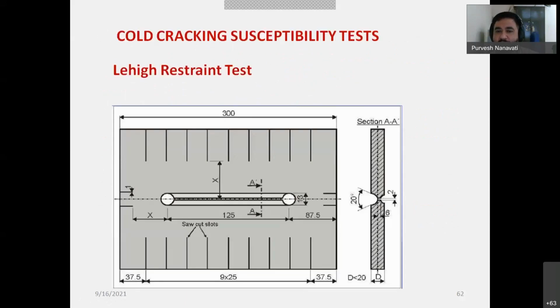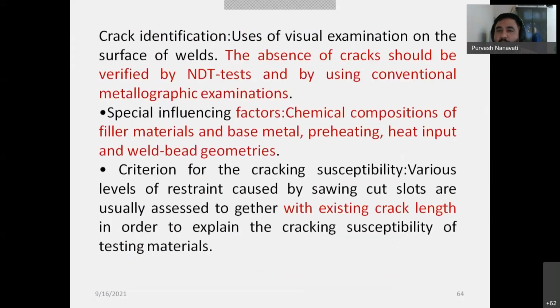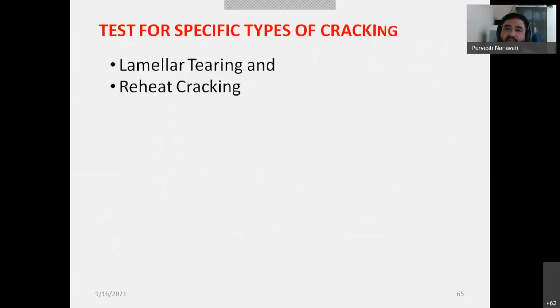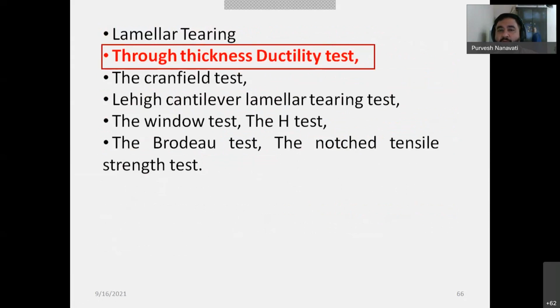You should observe these cracks by the NDT method when you perform this weld, because these cracks will be very fine in size, invisible to the naked eye. So you have to go for the NDT test and conventional metallography examination to detect the cracks, and you can work out the chemical composition of the filler metal and base metal, preheating, heat input and weld bead geometries using this test. Other tests are for lamellar tearing and reheat cracking. These are for the heat affected zone. One test is the through thickness ductility test, which is most of the time used for determining lamellar tearing.